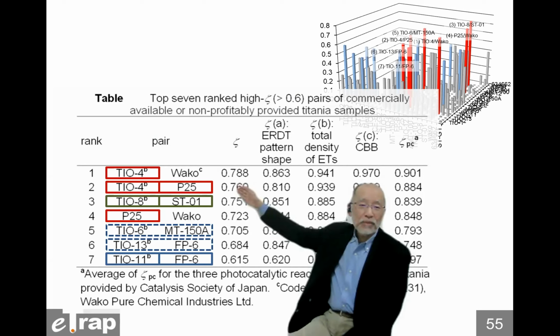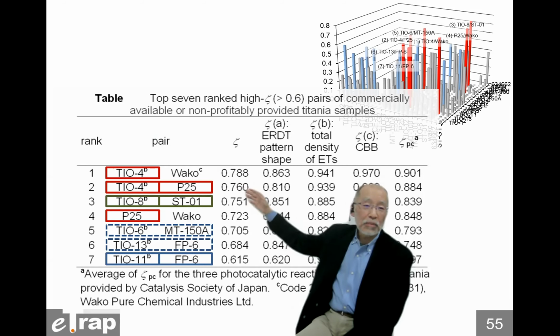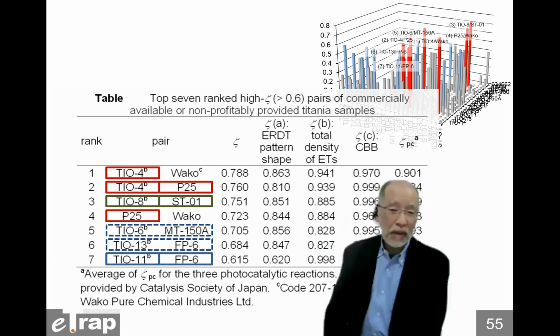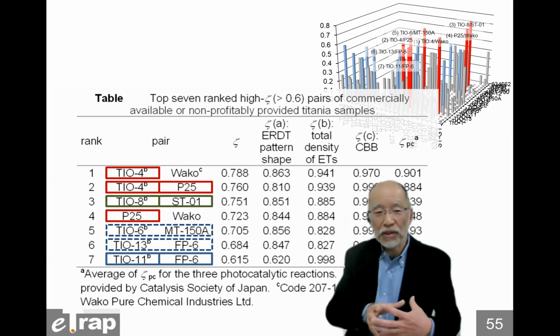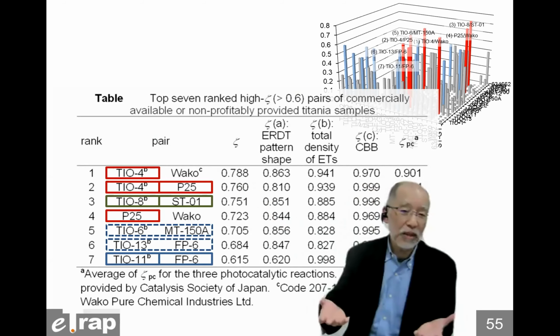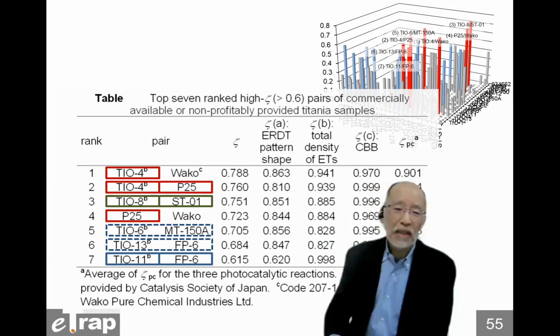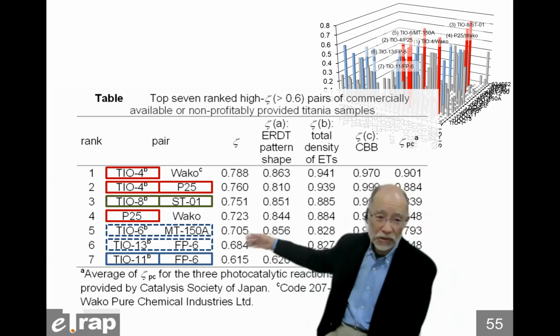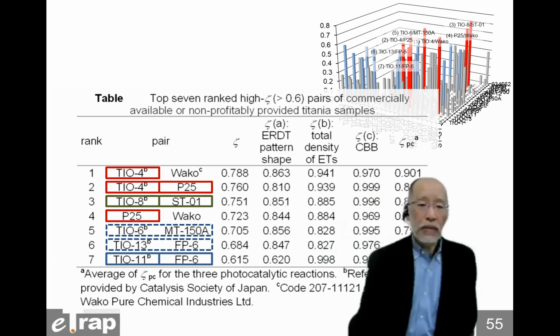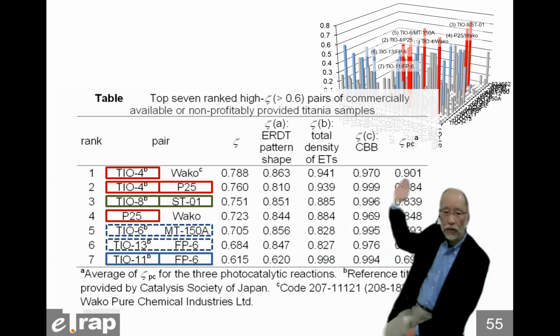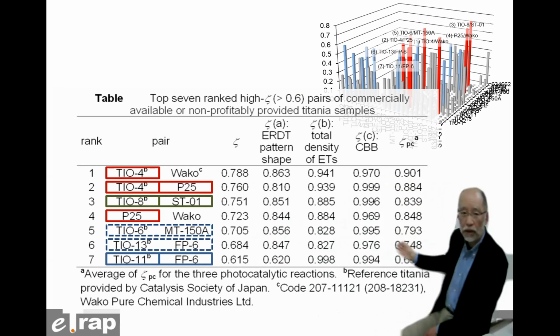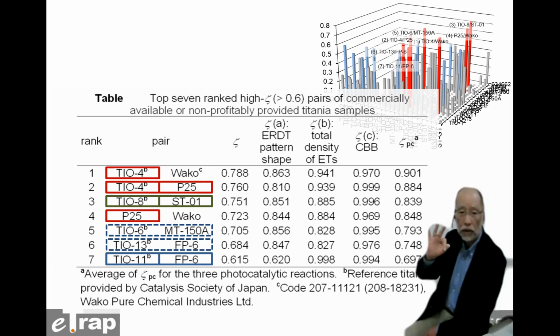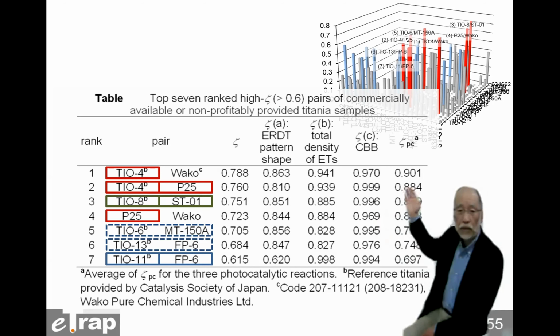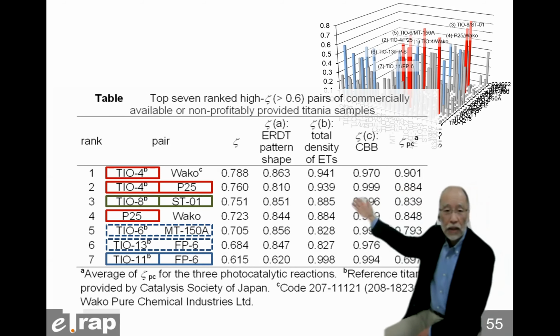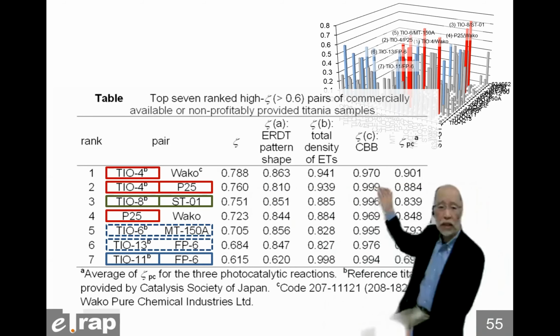However, even for the rank 2 one, the zeta value is 0.76, lower than 0.8. And remember that the same sample gives 0.9. So even with the same code name or the same product, a different production lot or different storage condition may give some difference. And the important point is that this column is the degree of coincidence of photocatalytic activity. This is the average of three photocatalytic reactions. That means if the activity is the same, it is 1. And the higher degree of coincidence pairs give a higher degree of photocatalytic activity coincidence.